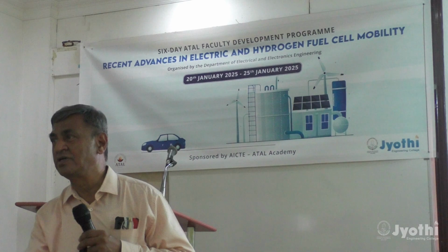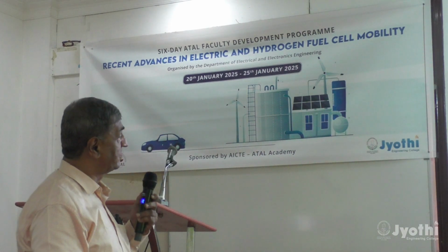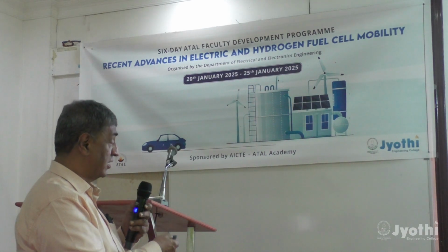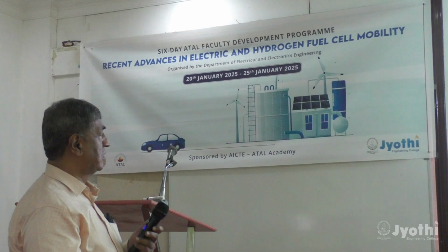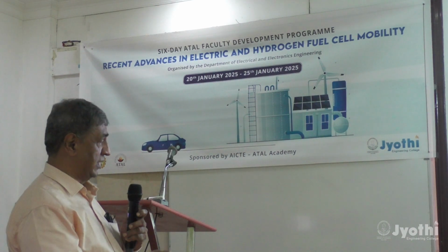After some use, it will fatigue. Particularly with catalyst, very often what will happen is after some 1 or 2 or few hours of operation, its activity goes down. But that was not happening here. We found that it was still quite active even after, let's say, lakhs of cycles done for a long time. So, as such, it turned out to be a good, stable catalyst which has bidirectional catalytic activity.